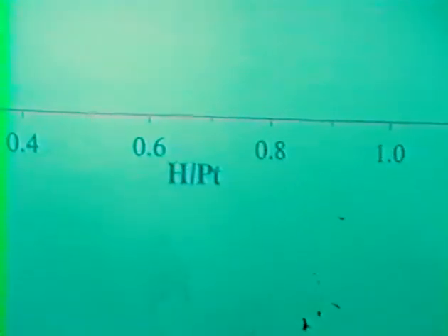But by the time we get to these 5 weight %, it falls distinctly off the correlation, because all of these have about the same coordination, but they have a distinctly smaller hydrogen chemisorption. Presumably that's because now the loading is so high that the probability of having a platinum particle at both ends of a parallel pore, which partially blocks it, is cutting down on the hydrogen chemisorption.